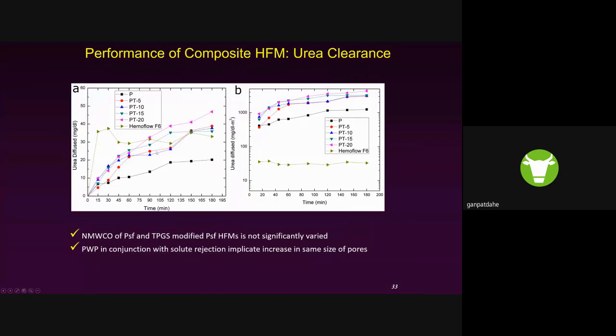Then we also did a urea clearance study using this hollow fiber membrane, and you can see that the urea clearance of the hollow fiber is very comparable to the commercial membrane. So indeed, this fiber can remove urea, and also if you look at the diffused urea per gram per square area, these fibers show a much higher value than the commercial one. This is quite exciting.